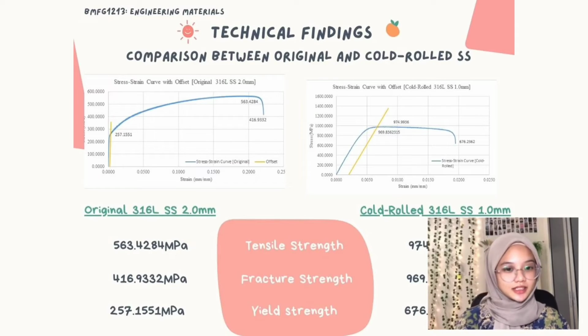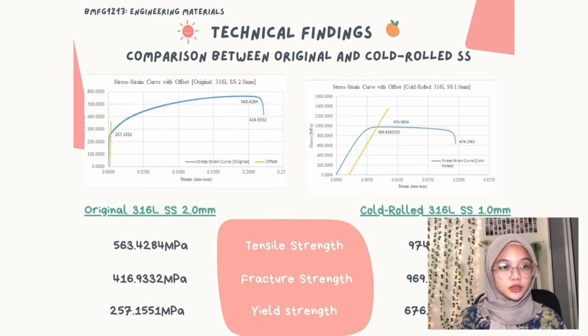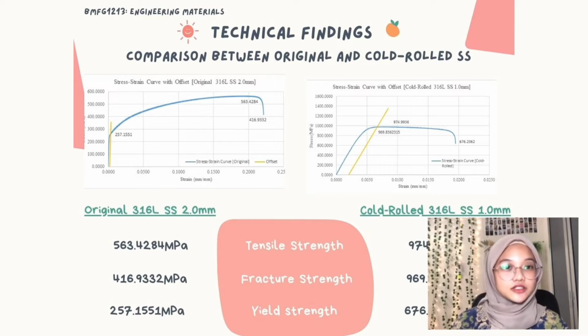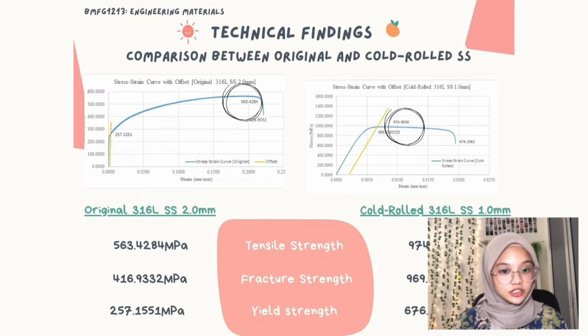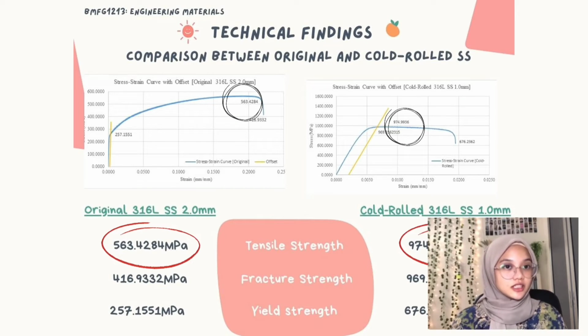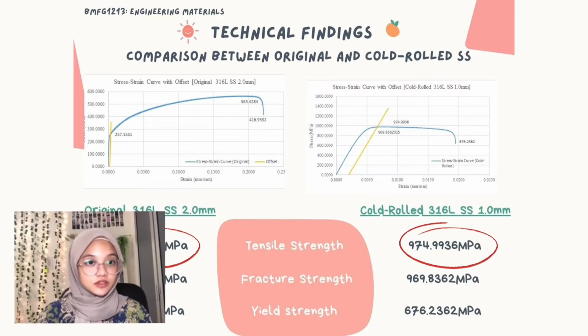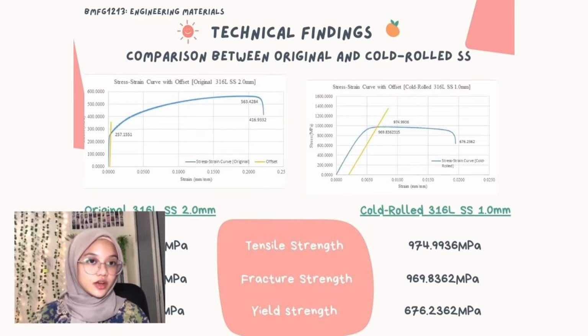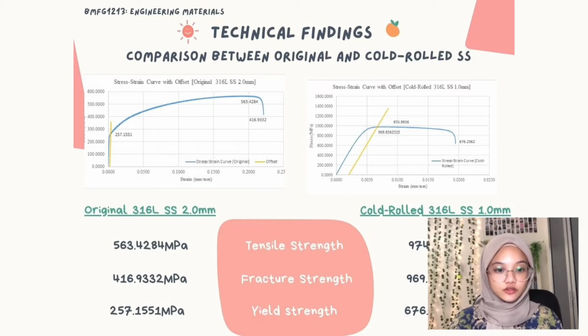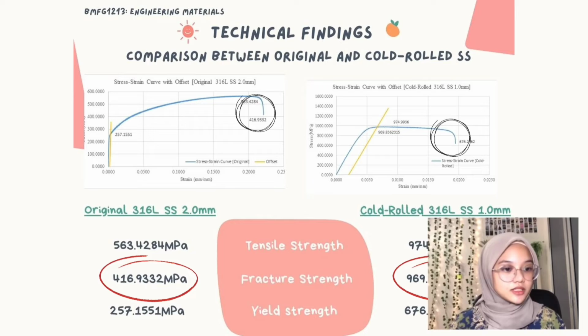Hello, I'm Hanis, and the technical findings are that the difference between these two specimens can be observed by performing two separate tensile tests on the original and the cold rolled specimen of 316L stainless steel. From the graph we can obtain the tensile strength from the maximum point of engineering stress, which is about 563 megapascal and 974 megapascal for the original and the cold rolled specimen respectively, while the fracture strength can be obtained from the value of stress at the point of rupture, which can be seen on the slide.